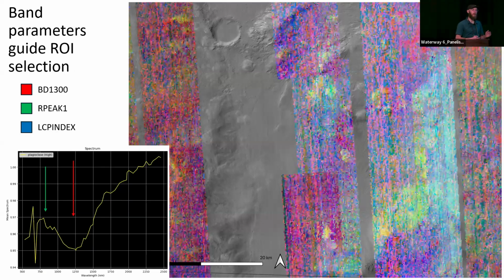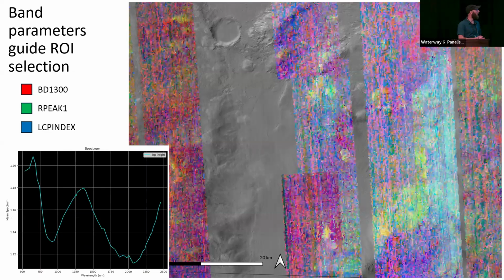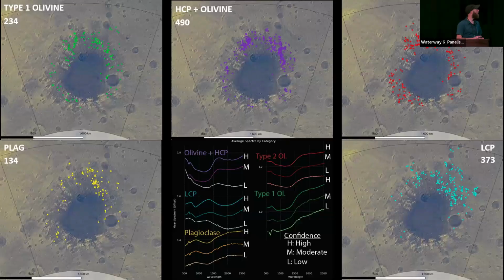And then the RPeak1 helps us differentiate these from olivine because you can see the reflectance peak ought to be longer wavelength for plagioclase than for olivine, and so these will show up as yellow. And the reason we track low calcium pyroxene is to avoid fake news in our spectra, where if you put LCP in the denominator, it'll basically make a fake plagioclase spectrum, so you want to avoid that.